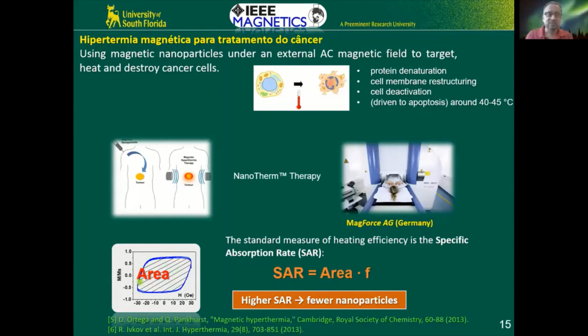And this is what we want to optimize or maximize, because for the specific absorption rate, like any other experiment, you need a figure of merit to find out what it is that you want to improve. And the figure of merit is the specific absorption rate, which is nothing but the area multiplied by the frequency. And you need to optimize this, keeping in mind that you need to get the highest SAR with the smallest number of particles, because remember that you're going to inject these particles inside the human body. So obviously you have to be very careful about how much you put in.